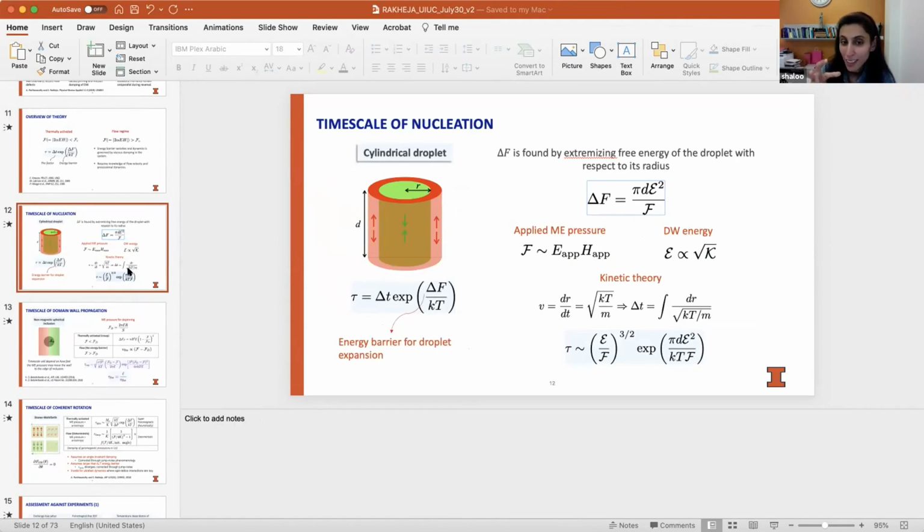We assume that there is this nucleation center that's present, and let's try to move it. And let's try to see if this will expand or not. And so if there is already a presence of defects, or maybe dislocations, maybe they could lower the wall energy, and maybe this nucleation center would exist. But if you're asking about a pure sample, I don't think, how would you cause this nucleation in an extremely pure chromia sample?